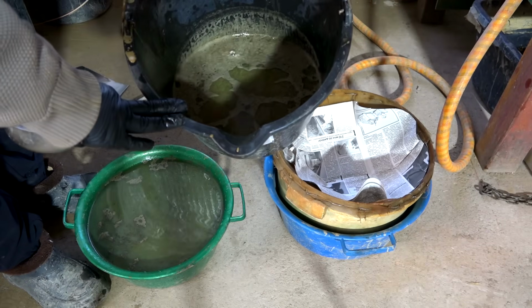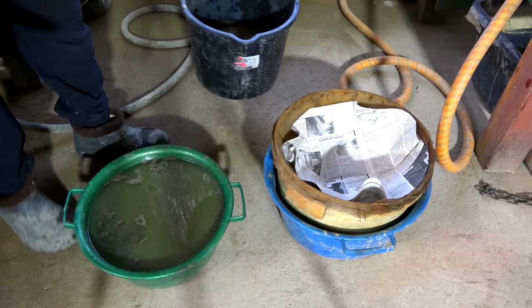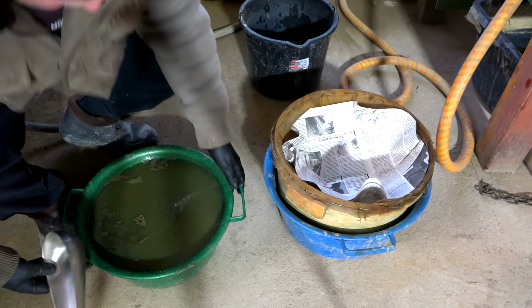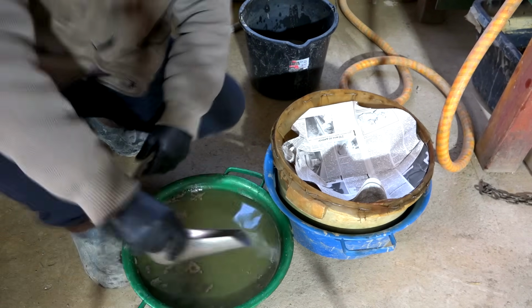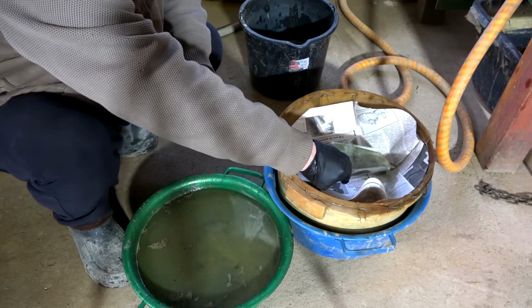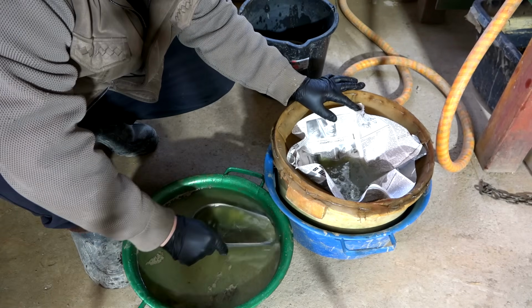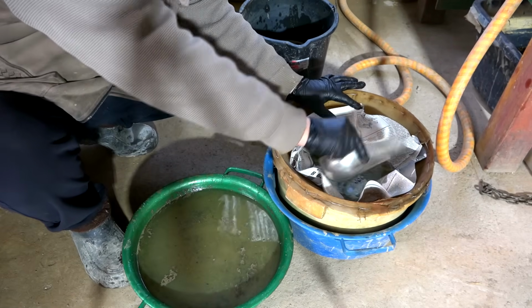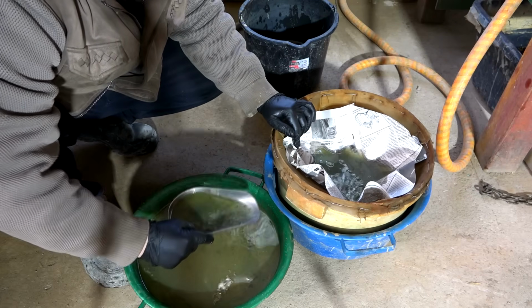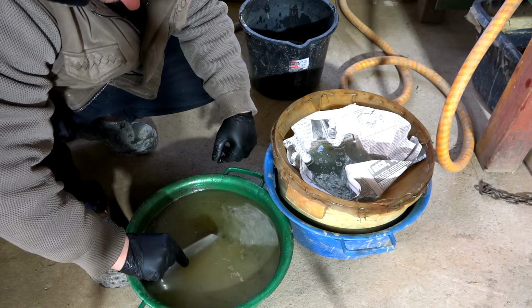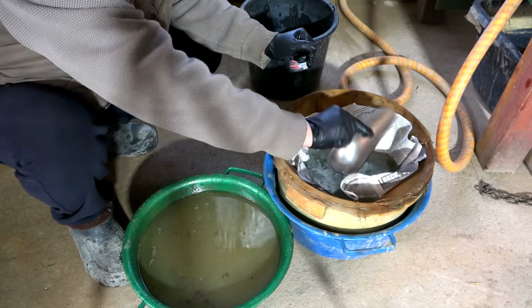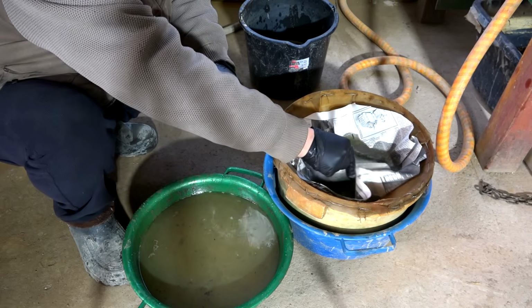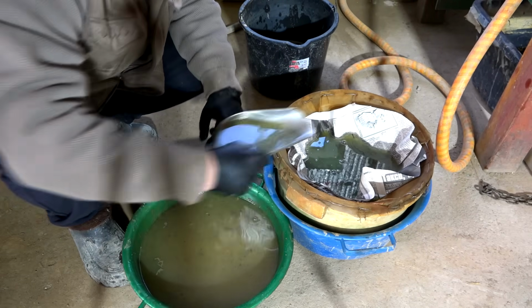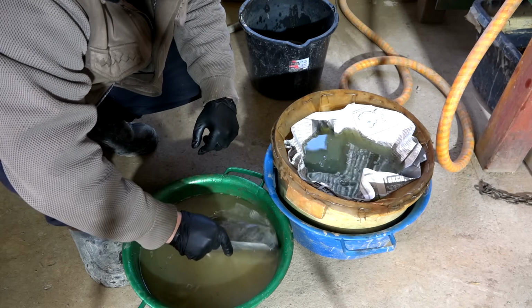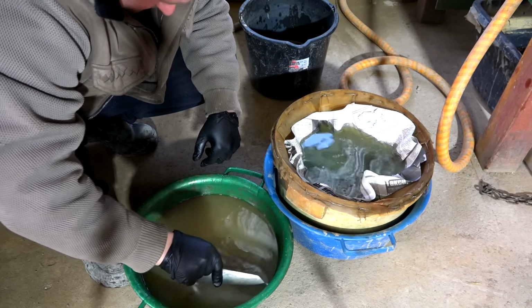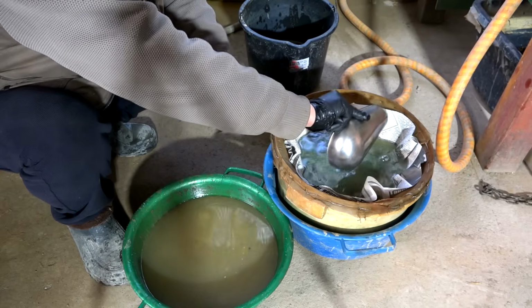I spent an hour on the flotation process, and it was time to filter the resulting concentrate. It's worth noting that the entire process had to be repeated the next day. The problem was that I was so absorbed in the process that I didn't notice that I was collecting not only the thick froth but also the pulp. After starting the filtration, I discovered a high clay content in the concentrate, so I decided to process it using the same method, using flotation. The second time, I tried collecting only the flotation froth, and everything worked perfectly.